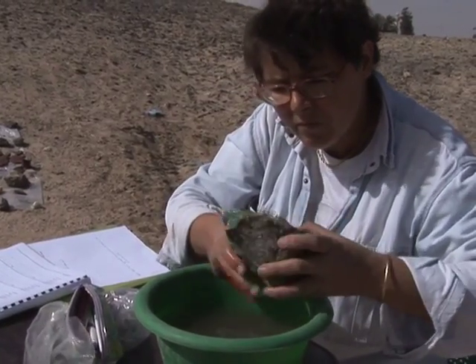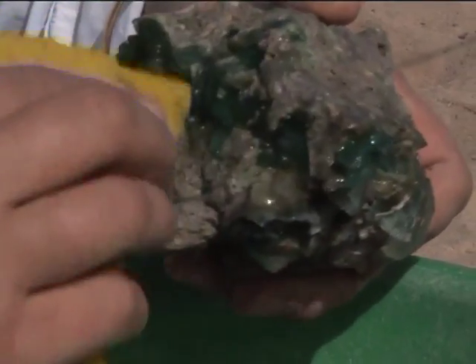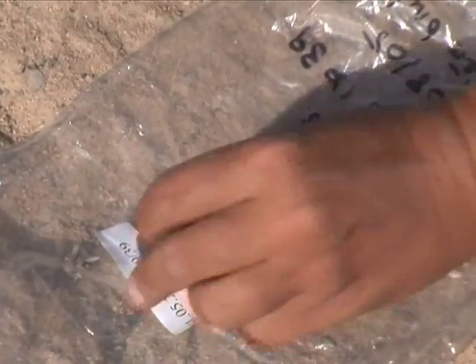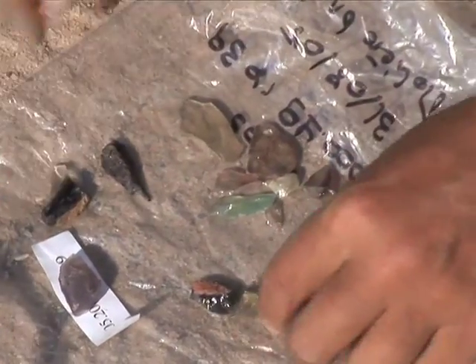The rare fragments of raw glass left on the site after the glass slab had been removed show that 3 types of glass were produced. A blue-green coloured glass and 2 kinds of colourless glass, one rendered so by the addition of manganese and the other by antimony.